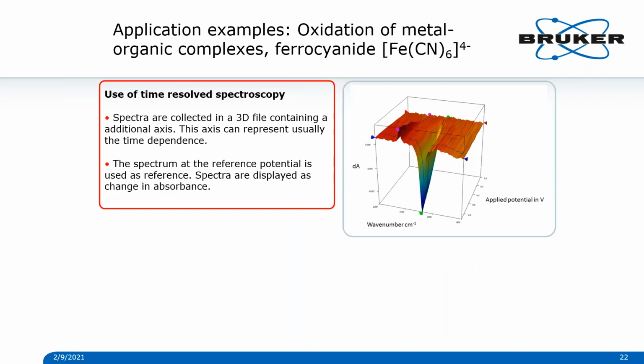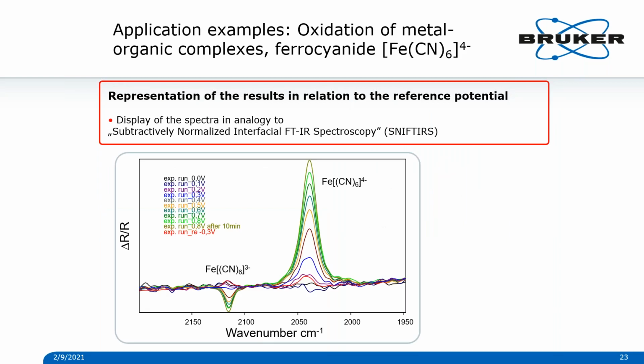So how we did this: we collected spectra at different potentials. There is so-called time-resolved spectroscopy, but in this case we have not used time resolution. We just change the potential, record a spectrum, and plot the spectrum versus applied potential. A typical presentation is that we subtract the spectrum at 0 potential and get a spectrum like this. You can see a few positive bands and some negative bands. Negative bands mean that the material is consumed during the reaction, and positive bands mean their intensity increases, meaning the amount of this material goes up during the reaction. As you can see, it's pretty clear which compounds go down and which compounds go up during this type of reaction.